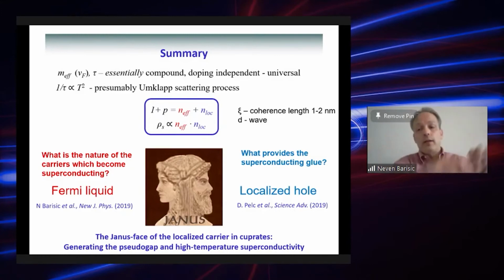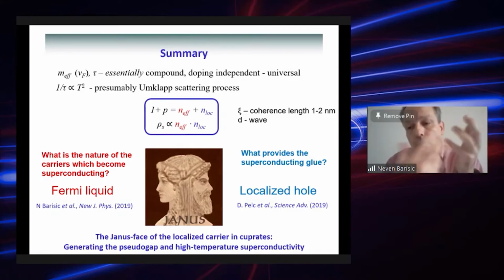We know the limiting case. We know that it goes from a non-Fermi surface to a full Fermi surface. Here, we don't have a single band model. We have a three band model. There are oxygens, and we know that holes start to go on the oxygens. So the question is how this Mott state survives in a three band model with strong disorder. But in essence, we think that behind this localization is a large Hubbard U of 10 electron volts, and this is the highest energy scale of the problem.